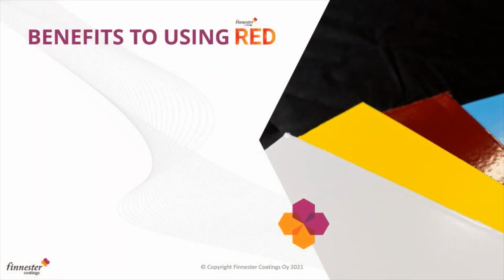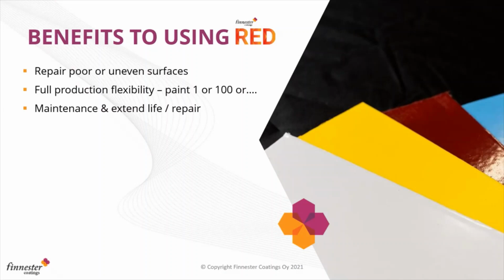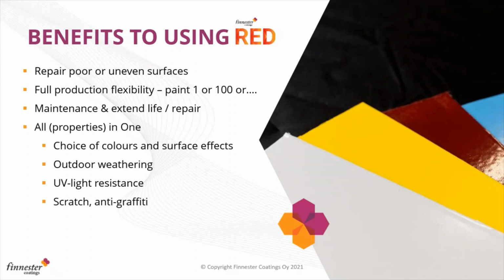So what are the benefits of using red coatings? Well, in any coatings, but also in red coatings, you can repair poor and uneven surfaces. If you demold something and there are some defects, you can easily patch them up, repair and finish it with the red. Also, you have full production flexibility, meaning that you can paint 1 or you can paint 100. If you have a standard composite case where you need 10 pieces, in a fire retardant case you need like 3 pieces. You can do the 3 FR and 7 not. And of course, you can maintain and extend the life of the composite. This is also the sustainability aspect, so you can extend the life of the current part.